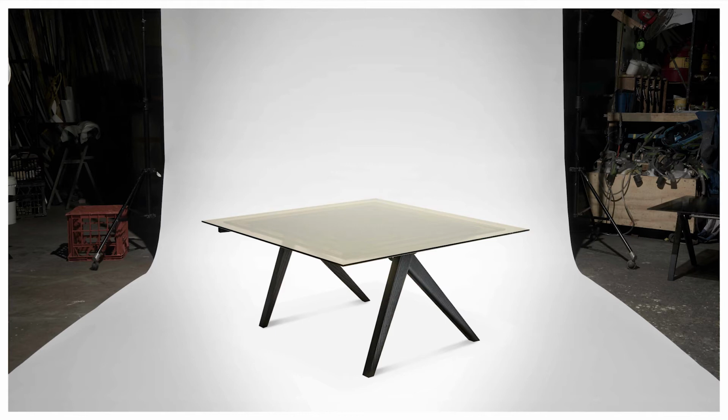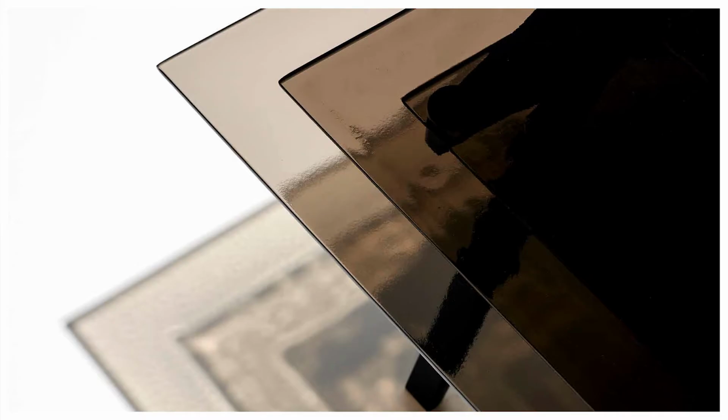So this was laid up in a kiln of sand and fired over 2 days at around 500 degrees, ramped down so that it wouldn't explode during the process. It was also fired and tested on lots of different beds, because we had the added challenge of trying to make the texture as smooth and flat as possible. And this is fired on sand, so it was a lot of fun. Good result. Yeah, I was thrilled.